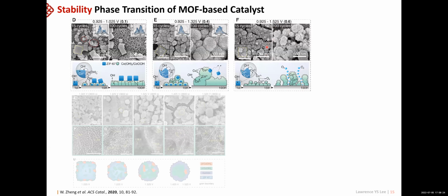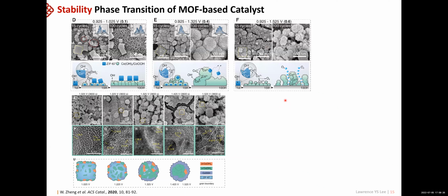The similar phenomena can be observed when we do the chronoamperometric experiment, which means we didn't cycle the potential. We only apply a certain potential and just hold it there for a long time. So here we hold the potential at 1, and here at about 1.5. We can see similar phase change, quite serious changes. So it's completely different species than we saw from the initial states. And we were able to identify some of the different species forming, making small domains.